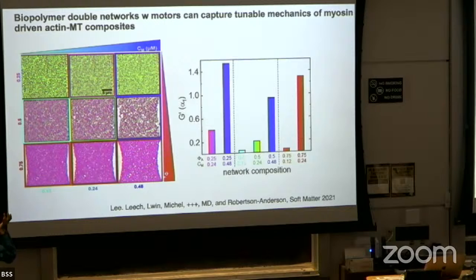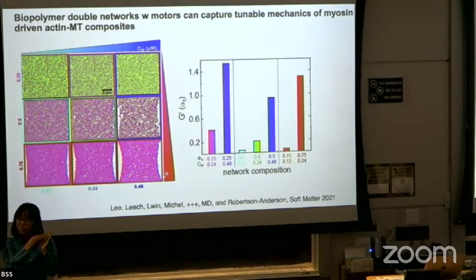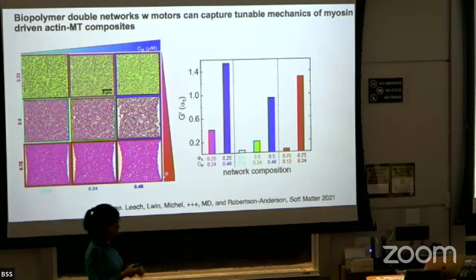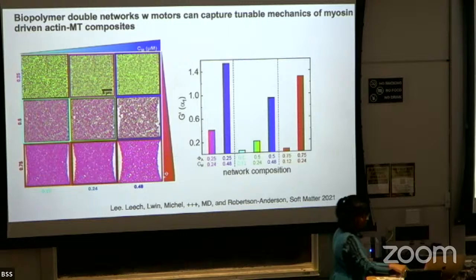Here the mesh size of both the networks, when mapped to experiments, are of the order of 200 to 500 nanometers in that scale. But what we did do is the ratio of the elastic constants like kappa 1, alpha 1, kappa 2, alpha 2. Those ratios reflect the ratio of stretching and bending in actin, stretching and bending in microtubules, versus bending in actin and bending in microtubules, right? Because bending in microtubules is 3 orders of magnitude larger than in actin, or stiffness, not bending itself.